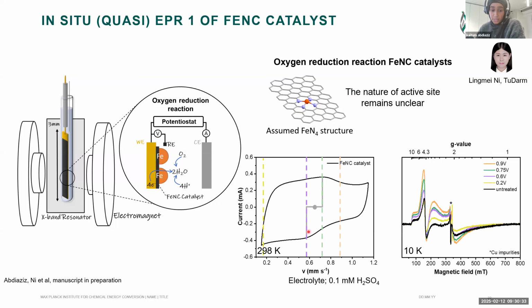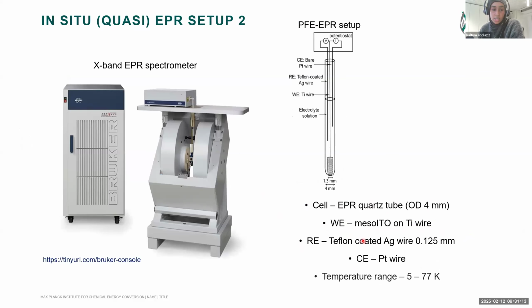I measured the CV at room temperature, and then I applied the potential at room temperature, and then I go to the EPR spectrometer and I measure the EPR. The one thing we did notice is that this signal is starting to disappear as you go from higher potentials to lower potentials. So it's electrochemically active. I won't go into too much detail since my talk is about the setup rather than the results of the application, but I hope that I showed you that with this setup, we have potential control over our system.